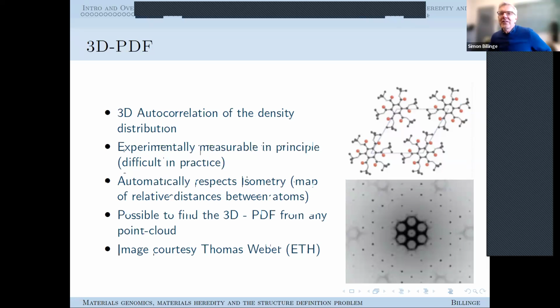It's interesting for us because it's actually possible to measure it in principle. In practice, it's slightly difficult to measure the 3D PDF, although we're actually getting better at it. But something we like about it is that this thing automatically respects isometry, because when you take the autocorrelation of the density, the absolute positions of the atoms no longer matter. It's only the relative positions of the atoms that matter. And so once you do this, you automatically have something that's isometry respecting. It's basically a map of the relative distances and vectors. Actually, in the 3D case, it's a map of the relative vectors between atoms. It's possible to compute in the forward direction. So given a three-dimensional point cloud, you can compute this object, and it's something that we can measure. So we like the PDF.